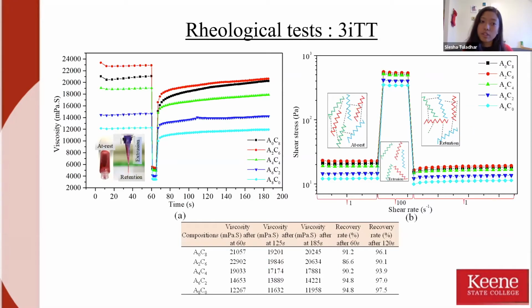Here is the thixotropic test, also known as the 3ITT test. On the graph on your left, you can see how this biomaterial is going to act when it is at rest, when it is at retention, and when it is extruding, when it's experiencing a certain kind of force. And on the right of the same graph, you can see how the biomaterial is going to heal or recover from its shear thinning behavior until it comes to a normal position or normal environment. For example, we can see that A0C8 on the graph below showed 91.2% of recovery after 60 seconds and 96.1% of recovery after 120 seconds.